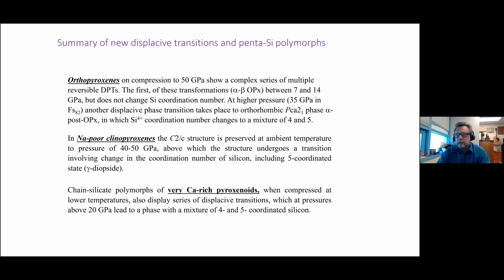And then the chain silicate polymorphs of calcium-rich pyroxenoids, when compressed at lower temperatures, also display a series of displacive transitions, similar to what we found in orthopyroxenes, which at pressures above 20 gigapascals lead to phases with a mixture of 4 and 5 coordinated silicon.